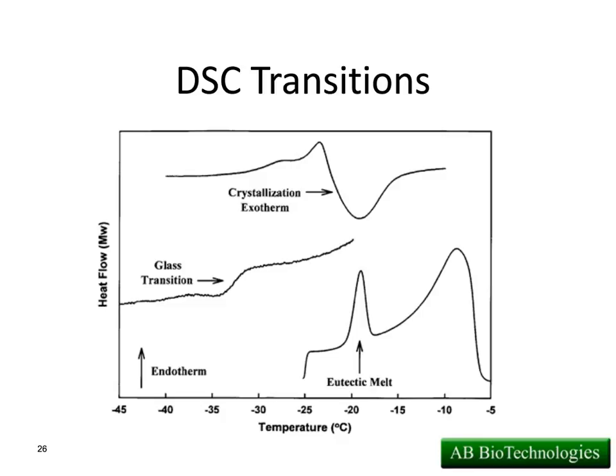Now, the software of our DSC calculates what we call the onset of the melt. So the leading baseline, the software will draw a tangent, and then the front edge of that peak, it will draw a tangent. And where they intersect somewhere below is what we call the onset of the melt. Now, let's look up here at the glass transition in the middle. You'll notice this is a completely different shaped curve. So it's what we call an S-curve. Well, the software draws a tangent to the leading baseline, a tangent to the trailing baseline, and the midpoint of those lines is what we call the Tg' of the glass transition. So again, just simply the shape of the peak tells us what it is, and then the software calculates the onset of the eutectic melt.